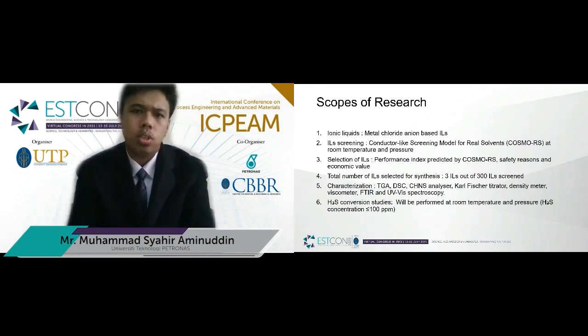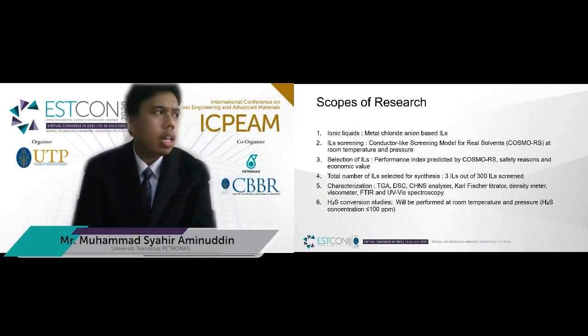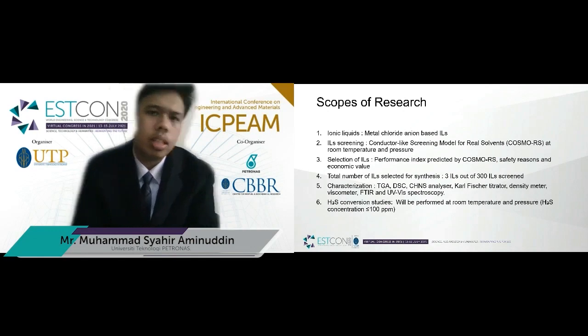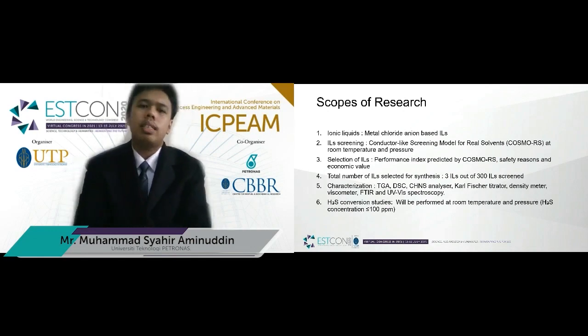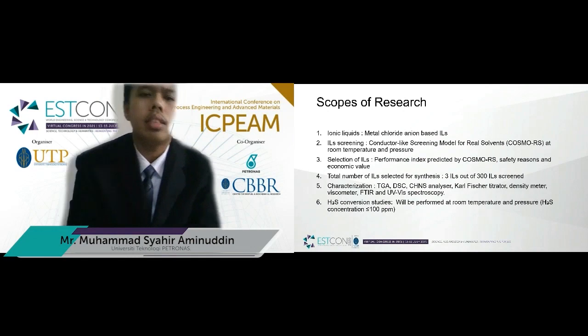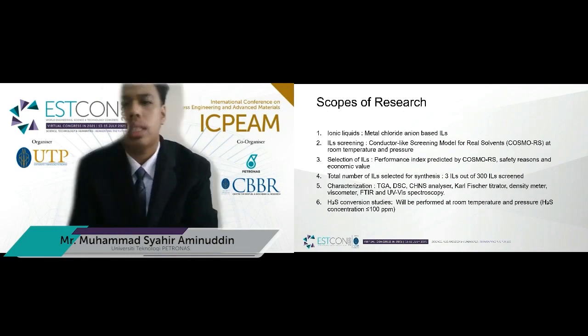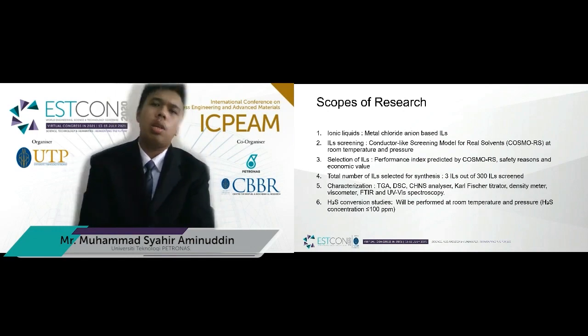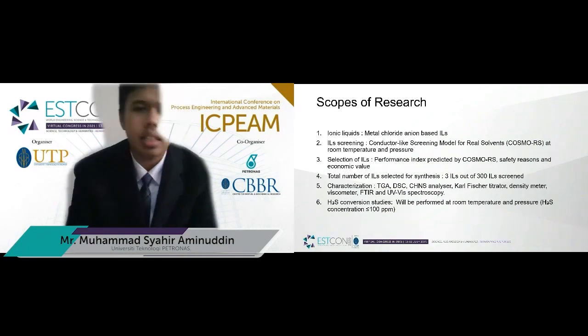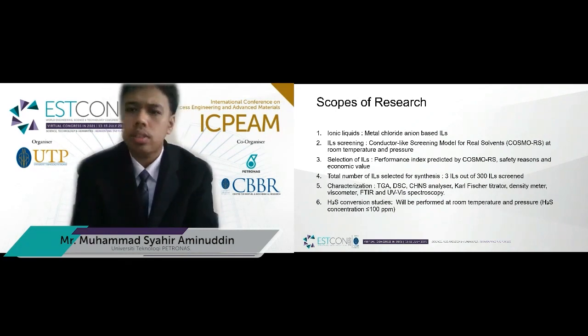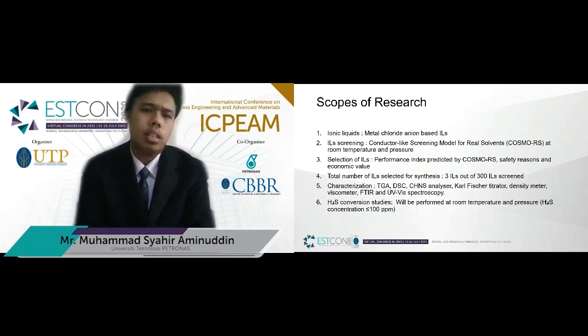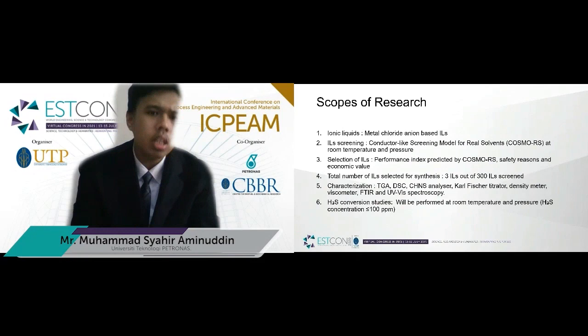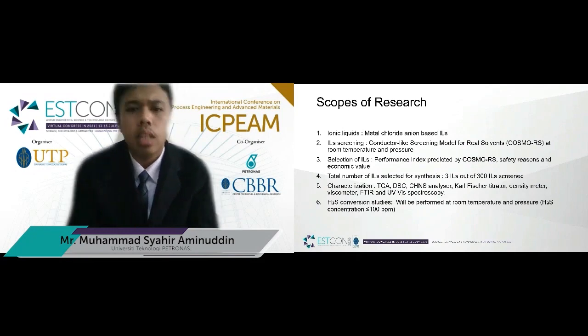The ionic liquids used are the metal chloride anion-based ionic liquids, and the screening will be conducted by the conductor-like screening model for real solvents, COSMO-RS, at room temperature and pressure. The selection of ILs will be based on the performance index, safety reasons, and economic value. The total number of ILs selected for synthesis is only 3 out of 300 ILs screened, and they will be characterized by the methods you can see here. The conversion studies will be performed at room temperature and pressure at a concentration of hydrogen sulfide lower than 100 ppm.